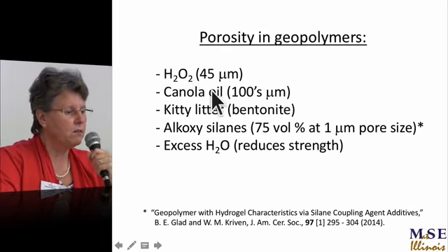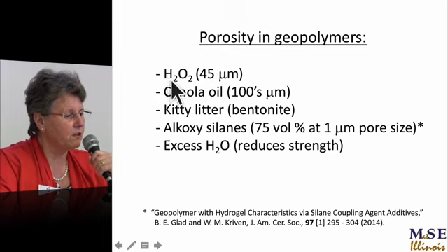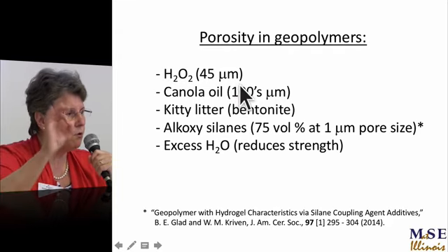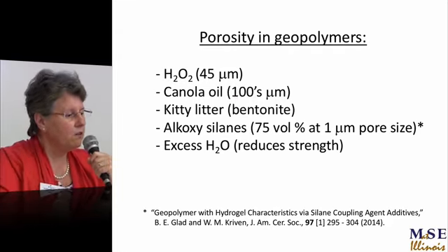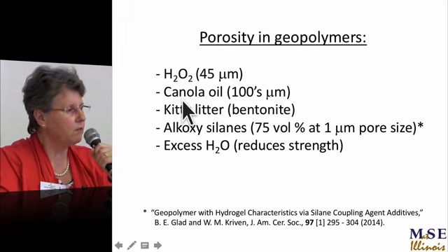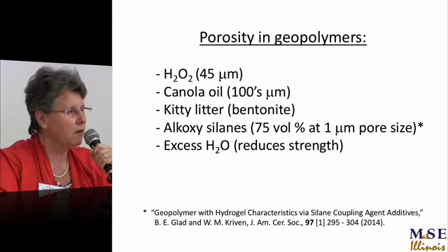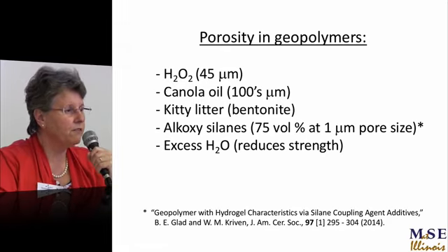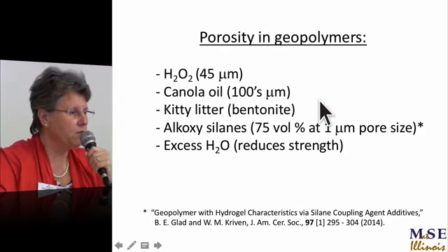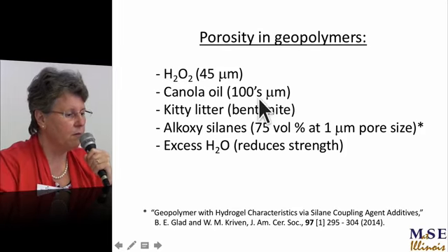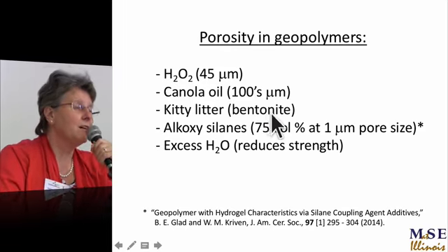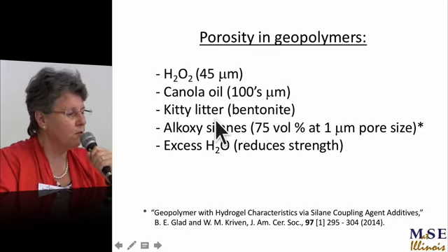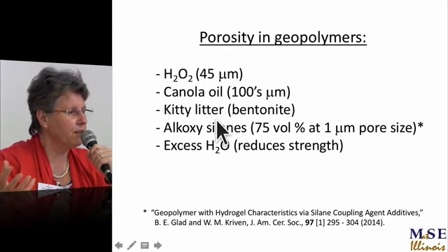And now porosity in geopolymers, right, people might be interested in using that for something. So if we add peroxide to it, you can get 45 micron pores in there. Don Sayo at Arizona State invented and got a patent on putting in cooking oil, canola cooking oil, and produced with sodium saponification, soap making, and he can make hundreds of microns pore sizes. And then he just washes the soap out, and it leaves a porous geopolymer. Other people have put in bentonite or kitty litter. That makes porosity like bread.